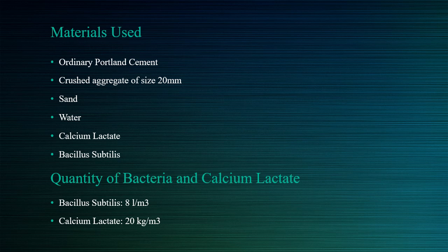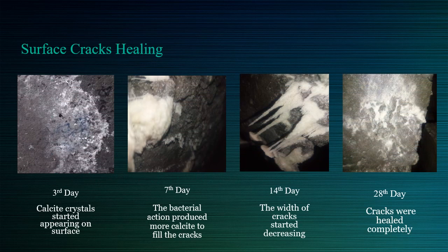The materials used are ordinary Portland cement, crushed aggregate of size 20 mm, sand, water, calcium lactate, and Bacillus subtilis. The quantity of Bacillus subtilis used is 8 liters per meter cube and calcium lactate is 20 kg per meter cube. And the surface healing of cracks.